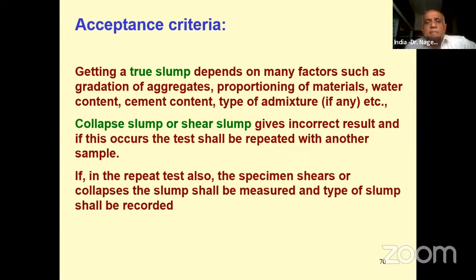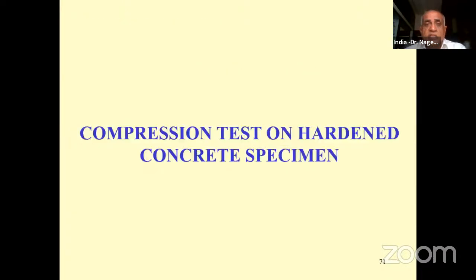Acceptance criteria. Getting a true slump depends on many factors such as gradation of aggregates, proportioning of materials, water content, cement content, type of admixture, etc. Collapse slump or shear slump gives an incorrect result, and if this occurs, the test shall be repeated with another sample. If in the repeat test also the specimen shears or collapses, the slump shall be measured and the type of slump shall be recorded. This can happen if the mix design itself is wrong; you can't expect a true slump in such cases. So if it is repeatedly failing, then you need to change the mix proportion, or sometimes the materials also. You should take a call as far as the failure of a slump test is concerned.